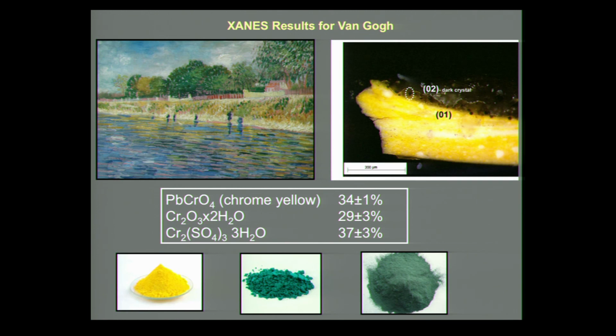And here are the results of the XANES analysis of the Van Gogh, and the analysis spot is shown here in this little oval in the brown area. And it turns out that it's about an equal mixture of chrome yellow, viridian green, and chromium sulfate, which when mixed together are forming this dark brown color. And so now that the degradation mechanism for this work is understood, a preservation strategy can start to be developed to preserve it for future generations.